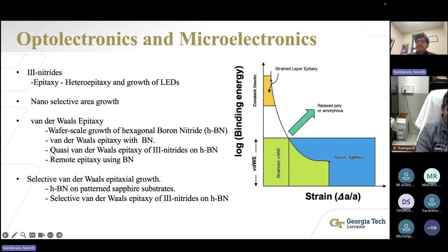So this graph is a one-stop shop for all the epitaxies we are doing here. So you can see that the region in yellow is where homoepitaxy and heteroepitaxy happens. So this graph is between the log of binding energy to the strain. So when we have covalent and ionic bonding, we have less room for errors, and we cannot move further. We cannot accommodate more strain. So if you are crossing certain limit, you are above the pseudomorphic strain layer formation, and then you will relax, forming polycrystals and amorphization.